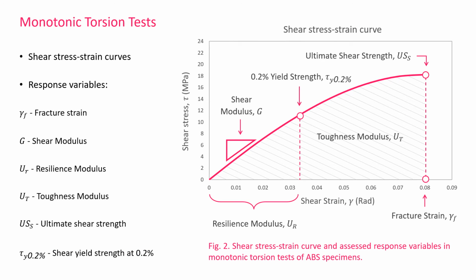From monotonic tests, shear stress strain curves, like the one shown in Figure 2, were obtained and shear modulus, shear yield strength using the 0.2% offset method, ultimate shear strength, fracture strain, resilience modulus, and toughness modulus were calculated and used as response variables to assess ABS specimens' mechanical properties.